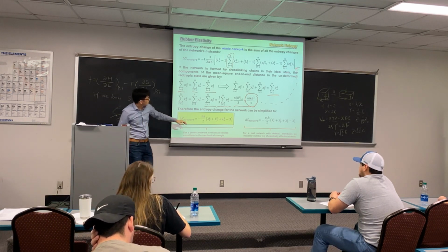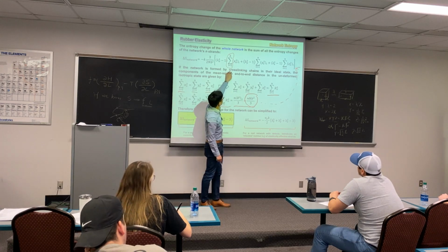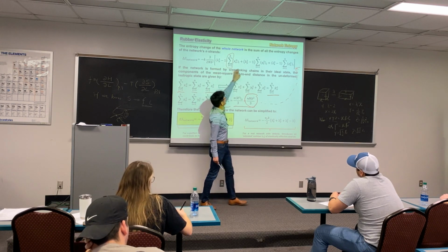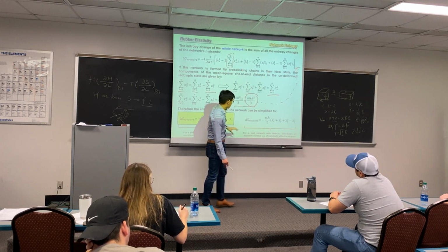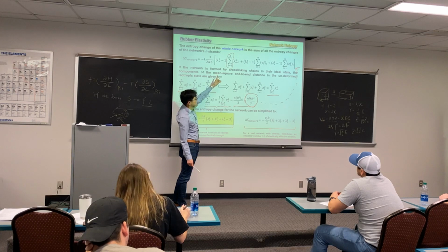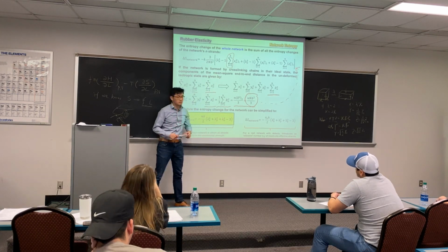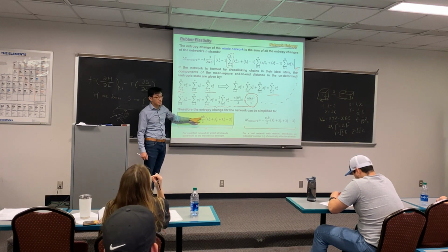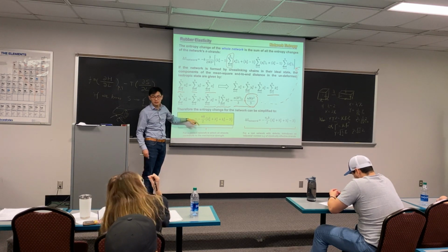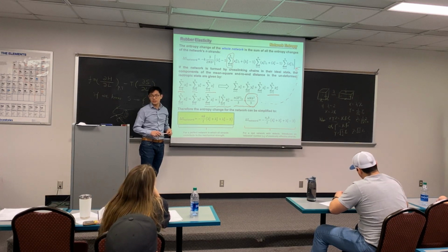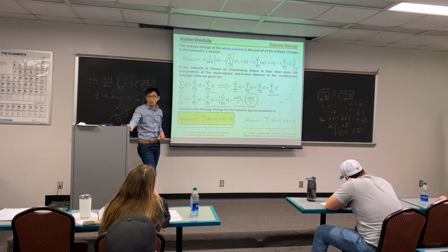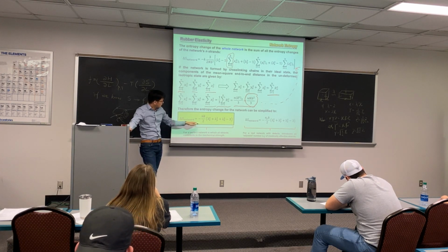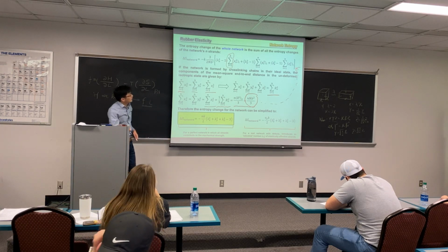Because when we apply this into the first term, we can group all the lambda x square, lambda y square, and lambda z square to here. And there's 3 minus 1 term that can be grouped into the minus 3. N is now the number of strands. So how many strands are in the system? If you have more strands, your delta S will be higher. K is the Boltzmann constant again.